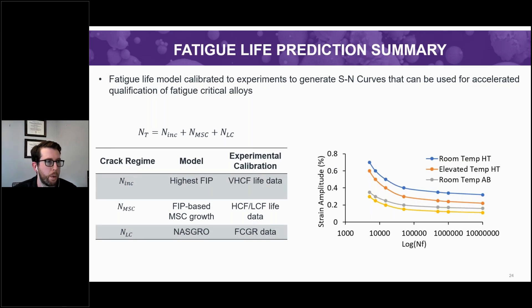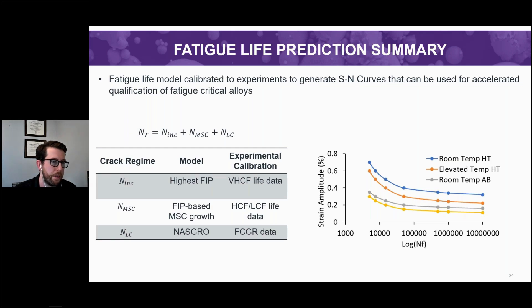To summarize this fatigue workflow, we split fatigue into incubation, microstructurally small crack growth, and long crack growth, and we have different models to capture each of these stages. You can see a summary of the different experimental techniques and models, with the resulting outputs being a full stress-strain curve as well as the full strain versus number of cycles fatigue life as a function of process, composition, and load environment.